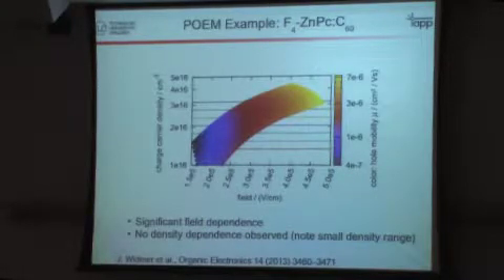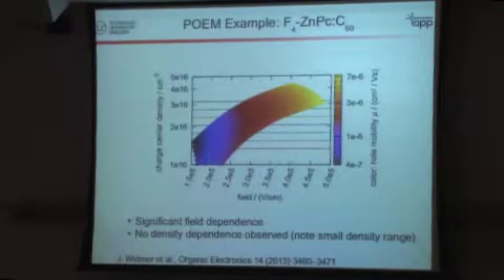This is a bulk heterojunction of a zinc phthalocyanine derivative with C60. And what you basically observe here is that in this material there is a quite pronounced field dependence. If you go for a constant carrier density to higher fields, you see that the mobility is significantly increasing. Whereas if you go at a certain field to higher carrier densities, you can see that the color code is virtually unchanged. So there's very little density dependence. However, in that measurement, the density was somewhat lower than it would be in a real device. But given that model now, you are able to analyze the mobilities and look at the very disappointing results. That was a bulk heterojunction prepared under the usual way we prepare a solar cell, and the mobilities are 10 to the minus 6 and not 10 to the minus 3, and that's the main problem we have in these materials.